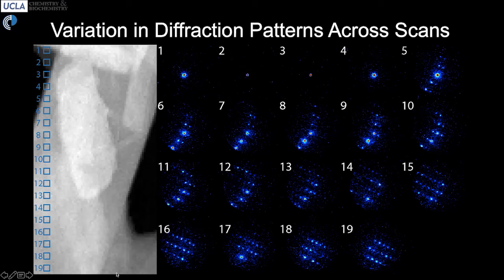The lacy carbon is down below and up above. And so it's sort of bridging across these segments of lacy carbon on a carbon wafer. As the beam is raster scanning across this whole area, you can parse out diffraction from these various areas labeled 1 through 19. What you can see is that diffraction over empty space just shows you the profile of the illuminating beam. So that's what the beam looks like that's impinging on the sample.